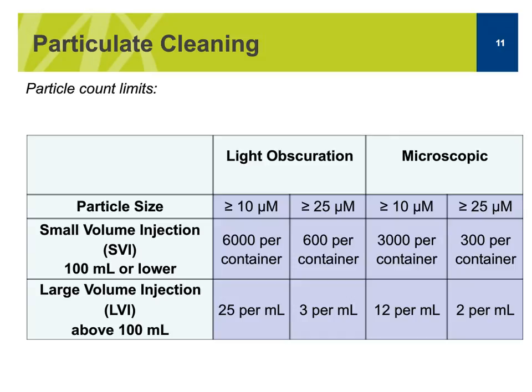For the microscopic method, particle sizes that are greater than or equal to 10 micrometer, small volume injections cannot have more than 3,000 per container, or 12 per milliliter for large volume injections. For particle sizes that are greater than or equal to 25 micrometer, small volume injections cannot have more than 300 per container, and for large volume injections, they cannot exceed 2 per milliliter.